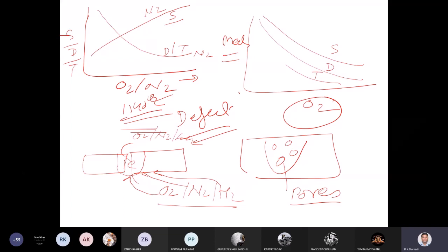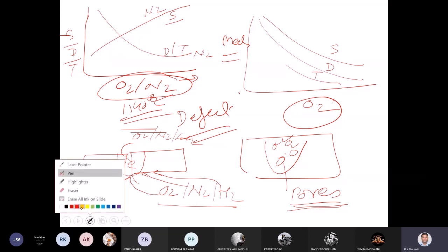Why? Because they have the affinity, they get dissolved easily in the molten state, and due to the high solidification rate during welding, they are not able to come out of the molten metal, and therefore they get trapped. When these get trapped, you find them in the form of pores. So not just the chemical affinity and the reactions leading to the formation of oxides and nitrides, but the gases also get trapped, leading to the development of pores. These pores and the inclusions are harmful for the joint strength or the joint properties.